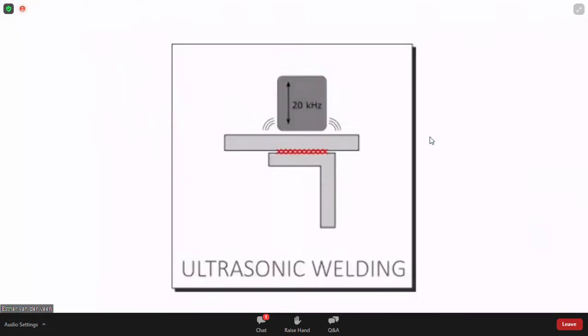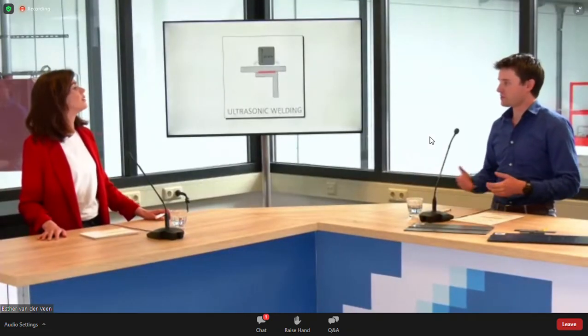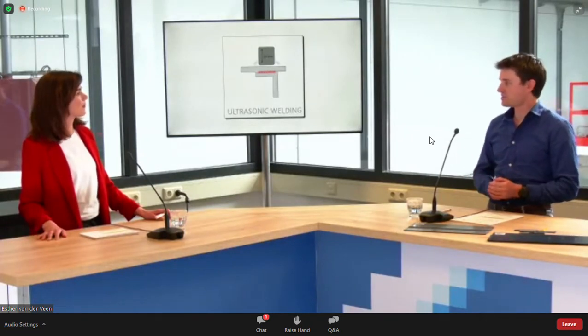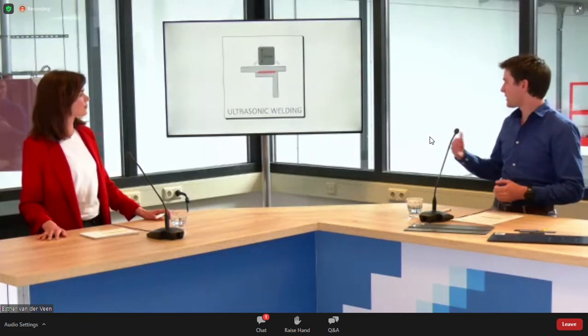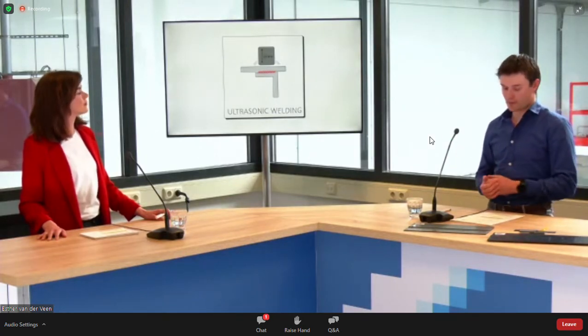Well, for instance, we have ultrasonic welding, where we apply a high-frequency vibration to our material. So locally, it gets heated at the interface. This is a very fast process and typically very well suited for spot welding, for example. It's a bit difficult because it's a discontinuous process, but our colleagues at the DLR and at the Technical University of Delft are working on making this process continuous.